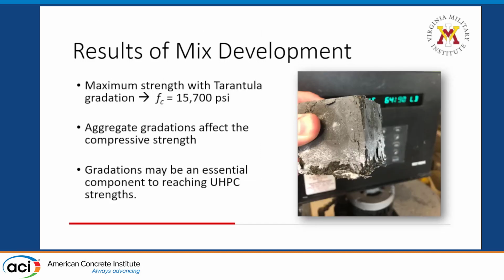So the results from the mix development: the maximum strength that we were able to reach was with the tarantula gradation, about 15.7 KSI. None of the mixes were able to reach the UHPC of 21.7 KSI with locally sourced materials, but all reached the high HSFRC category. They were strong concretes.